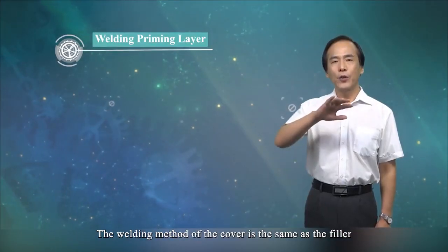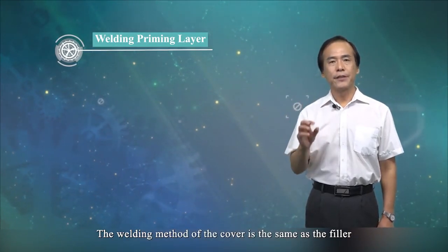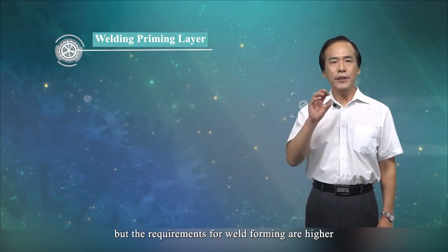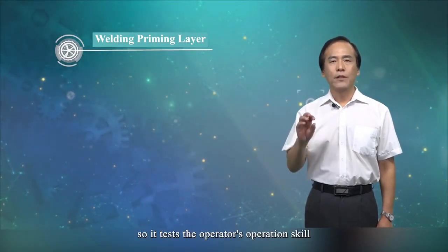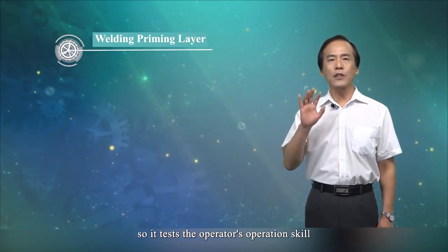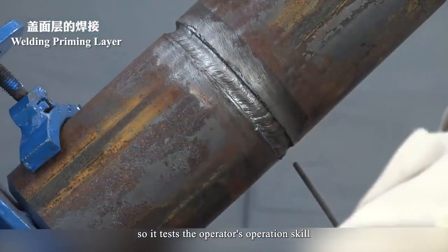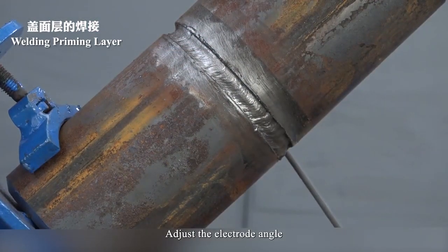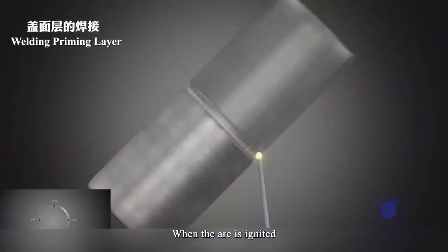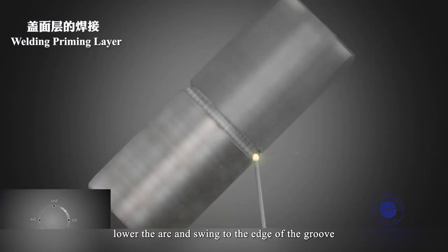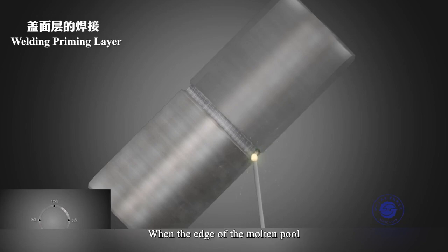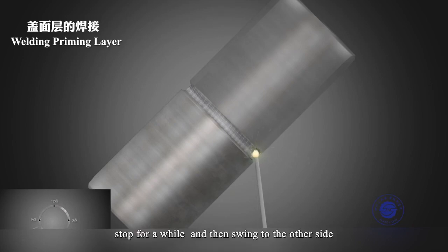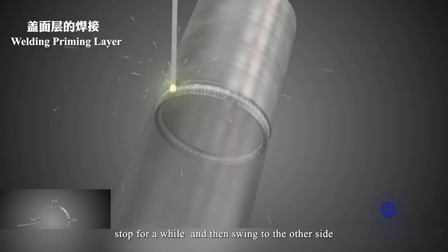The welding method of the cover is the same as the filler, but the requirements for weld forming are higher, so it tests the operator's operation skill. Adjust the electrode angle. When the arc is ignited, lower the arc and swing to the edge of the groove. When the edge of the molten pool just melts to the edge line of the groove, stop for a while and then swing to the other side.